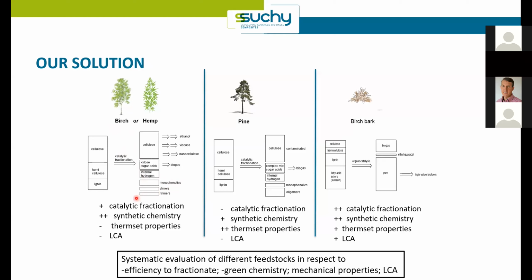So this is a little bit of a crowded slide, but you can see, for example, birch, the catalytic fractionation, that is the extraction, works pretty well. The synthetic chemistry works pretty well, but the thermoset properties were not good. So this will mean that we would have to use a lot of material to compensate for the poor properties. If we go to the pine instead, it is the reverse. So the catalytic fractionation does not work so well. We get a lot of waste products that we cannot valorize. And the synthetic chemistry works pretty well, and the thermoset properties are also very good. But because of this problem upstream, we cannot get a good life cycle assessment. The sustainability is poor.